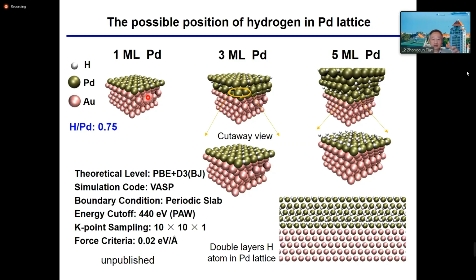So finding a spectroscopic method and evidence is still very difficult, because hydrogen is so small. Once it goes into the hollow or bridge site, the spectra just lose the signal. If we put a 3 layer of palladium, then we can get a kind of hydrogen adsorption. We cut off from this 3 layer to 1 monolayer. You can see the monolayer close to gold 111, and those bright spots belong to hydrogen.